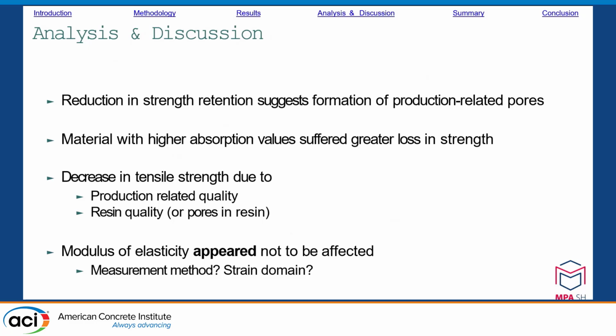Overall, it can be stated that the decrease in strength proves the formation of pores in the bars, which are due to the manufacturing process. Furthermore, higher saturation leads to greater strength losses. The reduction of the retention capacity is particularly evident in the basalt rods, which exhibited a high saturation in the preliminary tests. The test on transverse shear strength primarily examined the fiber properties. As the least changes were seen here, the fibers are not susceptible to frost.